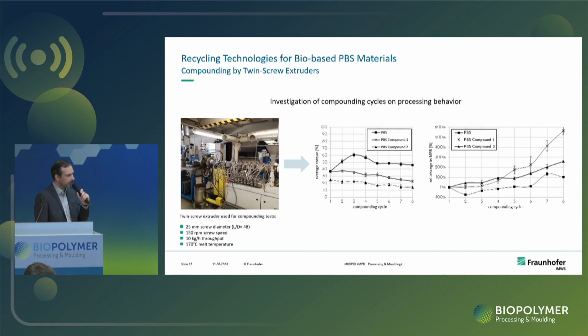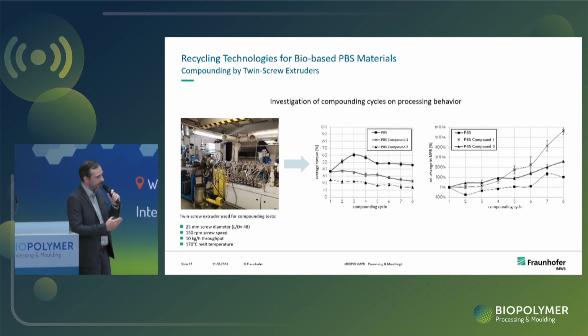So for the pure PBS, you see this slight increase in the torque. This is a known effect for a certain commercial product of PBS where there is a side branching during processing. But the torque afterwards is quite stable. We additionally investigated 2 different PBS compounds, and there you can see, yes,